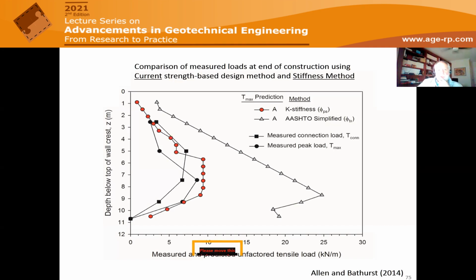But the essential outcome that you see here is the vertical scale is depth of the layer below the top of the wall. And the black symbols are the measured loads in the reinforcement. Now, if we use the simplified method, the old method, the predicted loads are way the heck out here. But when we use the precursor K-stiffness method to the current stiffness method, you can see that there was much closer correspondence between measured and predicted loads, and we didn't have this constant linear distribution that you would have predicted using the simplified AASHTO method.